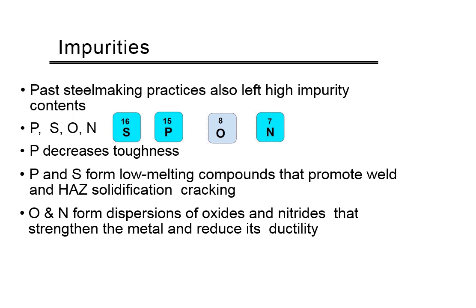So along with the things that we want in steels like carbon and manganese, there's also a lot of impurities that get left in there. If you look back on how they made steels in the 1800s, there were a lot of impurities before they figured out how to clean the material up. So sulfur, phosphorus, oxygen, and nitrogen are the biggies. Phosphorus decreases toughness. Phosphorus and sulfur form low melting compounds that promote weld and HAZ solidification cracking. Oxygen and nitrogen form dispersions of oxides and nitrides that strengthen the metal and reduce its ductility. So when they're making steels, you don't want a lot of sulfur, phosphorus, oxygen, or nitrogen in your weld pool or in your weld metal in general.